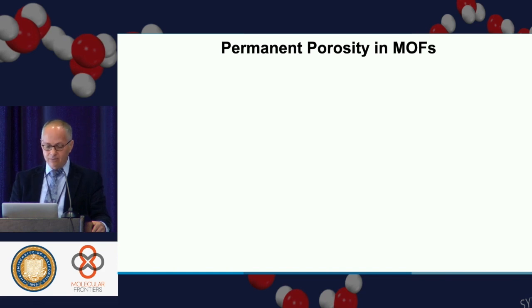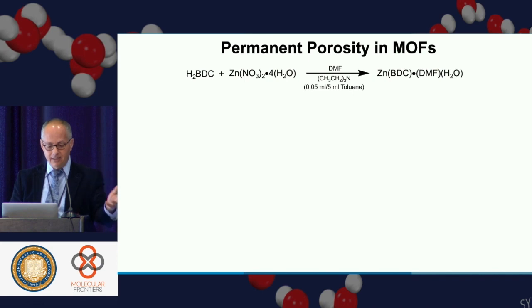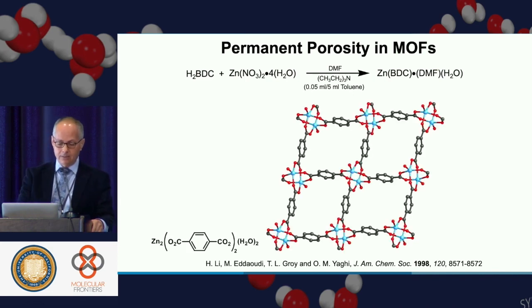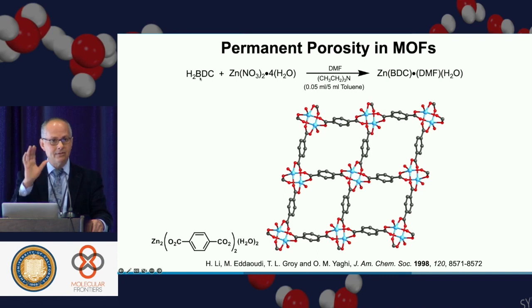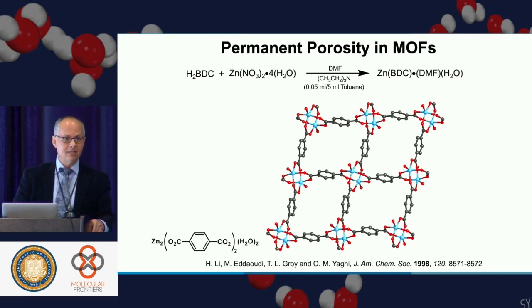So, okay, we were able to crystallize them, but now this is how the chemistry works. You take a metal ion, you have an organic linker, in this case, terephthalic acid, and you put in DMF, in this case with some amine, and you crystallize the material. The discovery here, the very initial way we discovered how to crystallize them, was that DMF, when heated, decomposes to make amine. And that amine then turns around and deprotonates the acid. And if you can control the rate of deprotonation, you can control this reaction, the crystallinity. And that was really what opens up this field. And it turns out that DMF, until today, is part of the cocktail of making MOFs. DMF or some other, like NMP or diethylformamide, very similar.